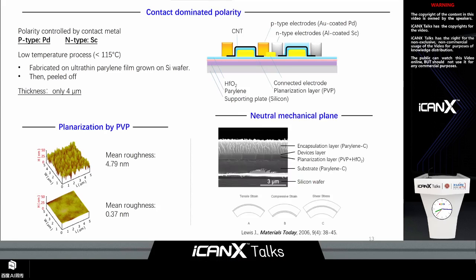Another thing we did is use PVP for planarization of the surface of the ultra-thin substrates. Before the planarization, the roughness of the substrate is very high, around 5 nanometers. After the planarization, the mean roughness can be reduced to below 1 nanometer, and such roughness has a great effect on the obtained device's performance. And thirdly, we use another layer to package our device so that all the active devices are in the neutral mechanical plane of the system.